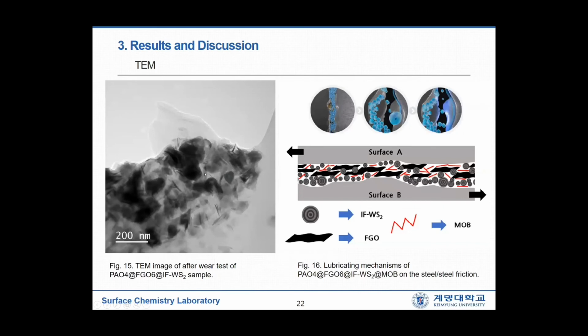Figure 15 shows the TEM image of the lubricant sample after finishing the friction test. In this figure, you can see the TEM image displays IF-WS2 inside and the FGO sheet wrapped around IF-WS2. This result indicates that IF-WS2 acts as a ball bearing between FGO sheets. Figure 16 shows the lubrication mechanism of FGO, IF-WS2, and MOB. This figure suggests that the wear track in the contact surface was filled with IF-WS2, and IF-WS2 was introduced between FGO sheets, thereby serving as a ball bearing, resulting in lubrication. In addition, the gelator, MOB, fixed the additives of FGO and IF-WS2 to prevent agglomeration and sedimentation, and eventually maintain dispersion of these additives.